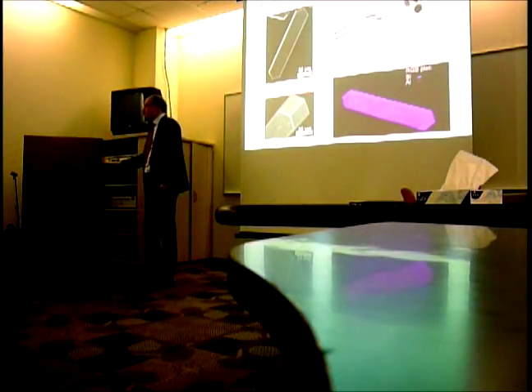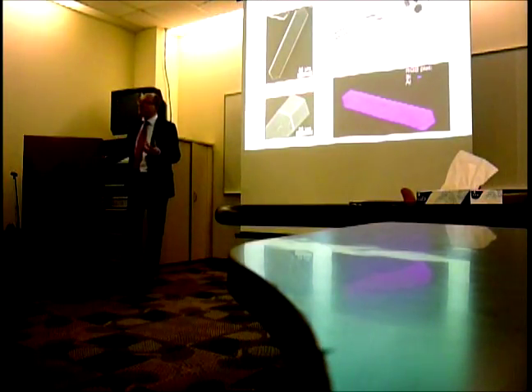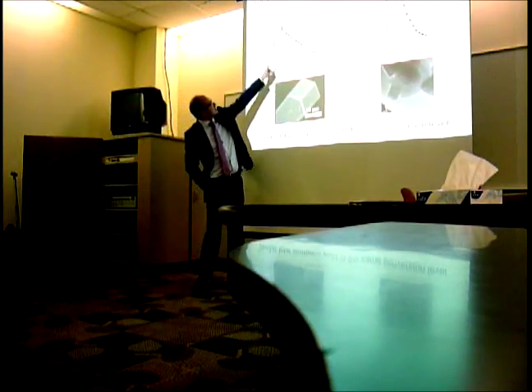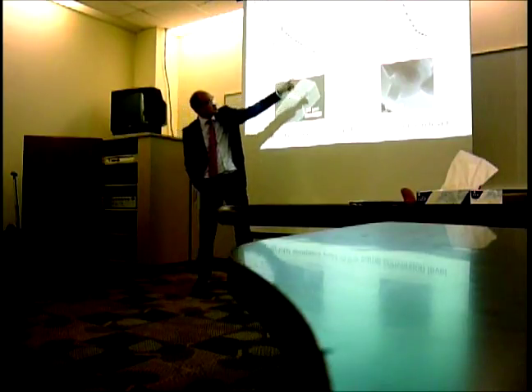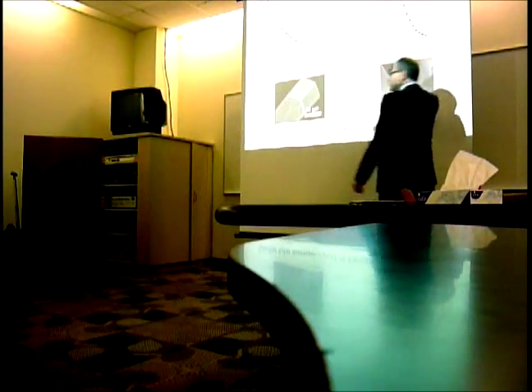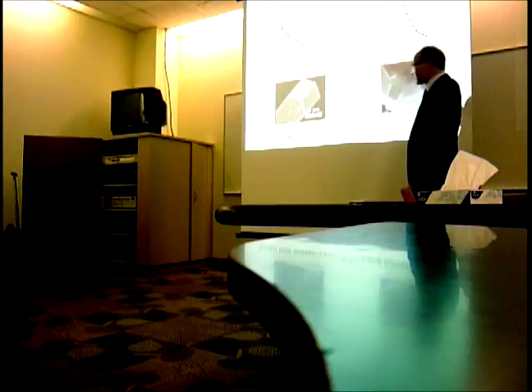It's on the methanol to hydrocarbon process, and what we have been doing is using again these big zeolite crystals. Now with these big zeolite crystals, you can ask yourself, are they good models to study the methanol to hydrocarbon process? And the first thing is, just test them. So what we did is, here we have the big zeolite crystals, and this is the conversion as a function of time, and this is an industrial sample, a small sample.